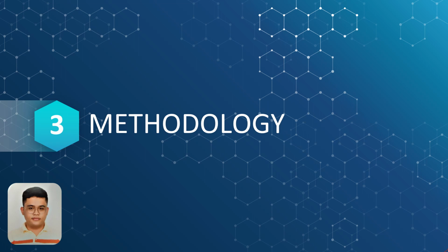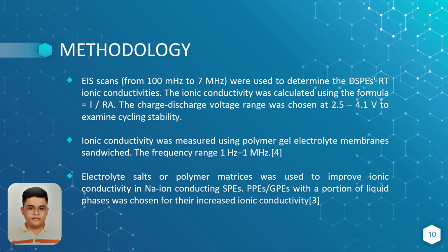I will explain about the methodology for this sodium polymer battery. For the first methodology, electrochemical impedance spectroscopy scans from 100 mHz to 7 MHz of a cell with stainless steel electrodes in the configuration of SS, DSPE, SS were used to determine the DSPE room temperature ionic conductivities. The ionic conductivity was calculated using the formula l divided by RA, where l is the electrolyte membrane thickness, R is the bulk resistance, and A is the contact area between the DSPE and SS. The LSV data collected using an SS, DSPE, Na cell was used to evaluate the DSPE electrochemical window. The charge-discharge voltage range was chosen at 2.5 to 4.1 volt to determine cycling stability.